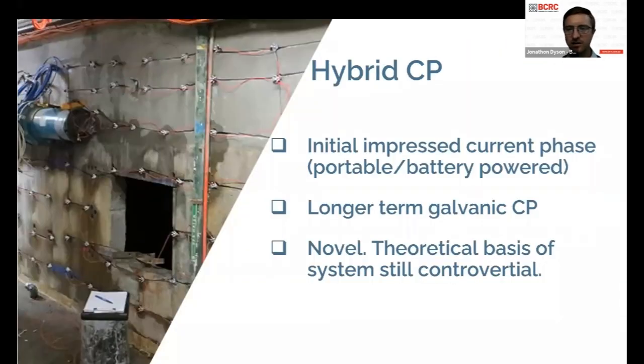So hybrid cathodic protection is where you have an initial impressed current phase, which may be from a portable power supply or from battery power. And once you've charged up the structure with a relatively high level of current and you've achieved a good potential shift in the reinforcement, you then switch over to a longer term galvanic cathodic protection system. So this is quite an innovative and novel approach. It's been around for a decade or longer now, but it's relatively new compared to the other techniques. However, there is still some controversy around the theoretical basis of the system in some papers, etc.